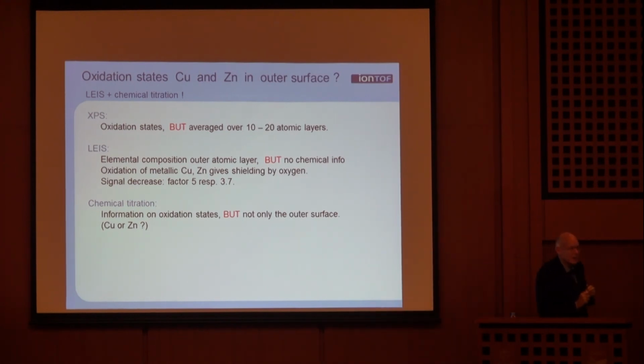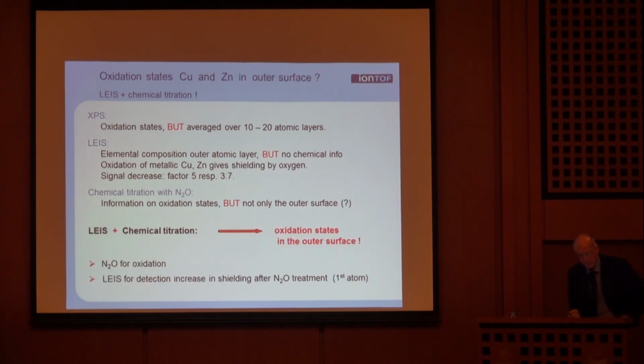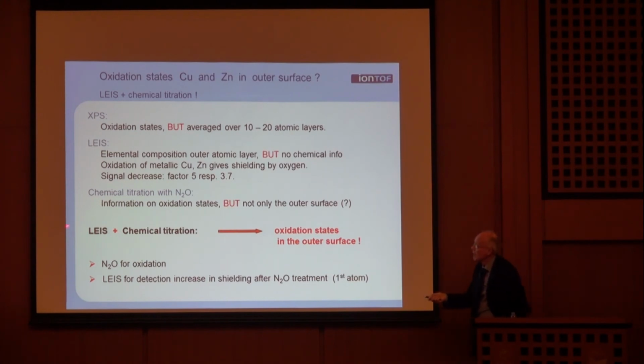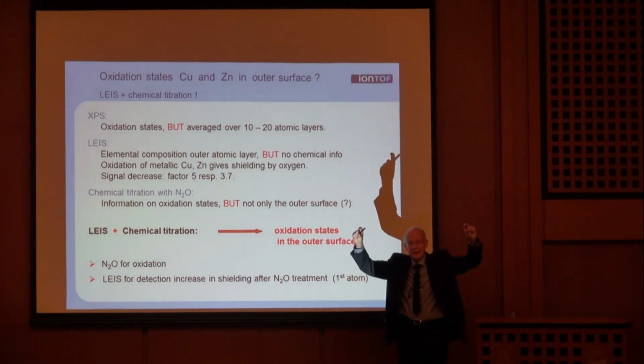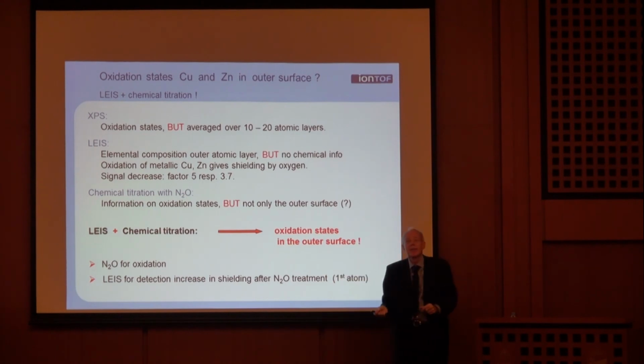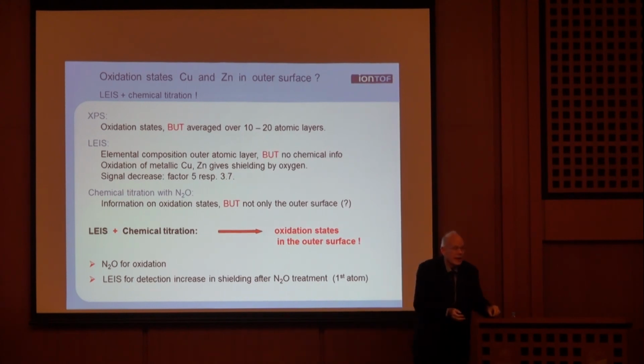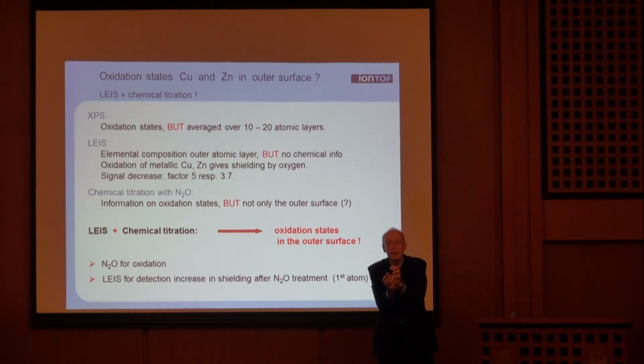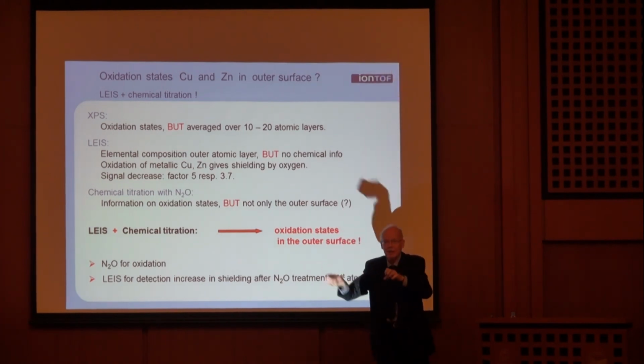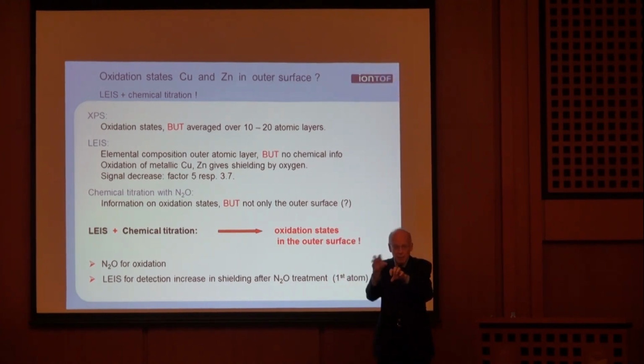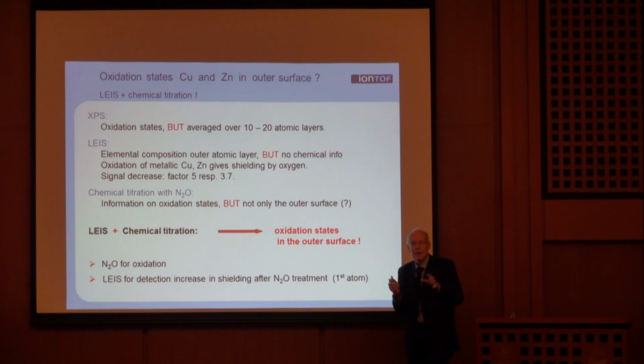Now, what I suggest is to combine these two techniques. On the one hand, I use ion scattering to look at the top layer. On the other hand, I use chemical titration to change the oxidation state. And now you should realize that if I have metallic copper, it's very easy to scatter from it and I get a high signal. If I oxidize copper, it is partially surrounded, screened by oxygen atoms. Because of that, I lose a factor of about 4 if I oxidize copper.